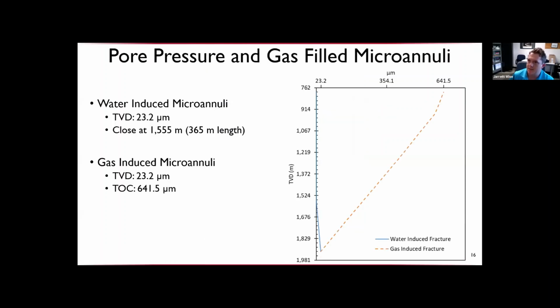The point of this talk is, how does the top of cement affect the leakage path? Using the method described a few slides ago, we can determine how the microannuli propagates up the wellbore with the gas fracture pressure, as shown by the orange line on the screen. And for comparison, we used basically water in the fracture, so just the pore pressure of the water with water density and all the good stuff with water. That's shown by the blue line on the screen.